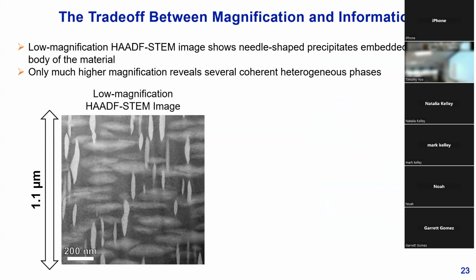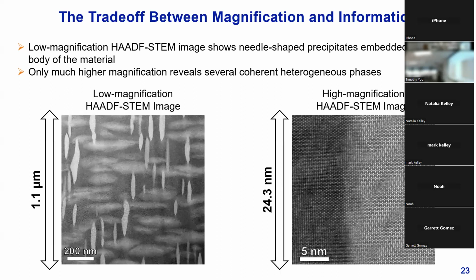And so here we quickly start to see again the problem where we get a trade-off between magnification and information. On the left here, we have a relatively low magnification STEM image. Note that the field of view here is about 1.1 microns. We can see that it's characterized by these bright needle-shaped precipitates embedded in the body of the alloy. And only at much higher magnification, almost by a factor of 40, can we now start to resolve different atomic structures, from which we can see what kind of phases are present and coexisting in our sample.